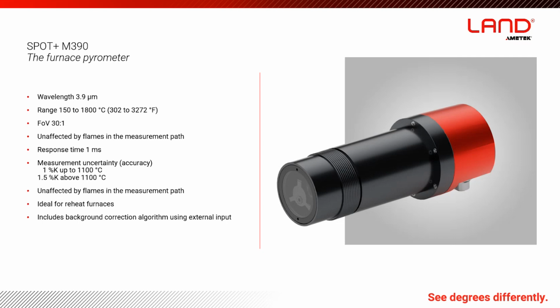And we're describing the SPOT Plus M390 as the furnace pyrometer. That's because its 3.9 micron wavelength is a spectral window in furnace applications. There is nothing in a typical furnace atmosphere that absorbs and emits at 3.9 microns. So it doesn't matter if you've got hot carbon dioxide, hot carbon monoxide, you've got visible flames there. To a pretty large extent, nothing interferes with the measurement at that wavelength.